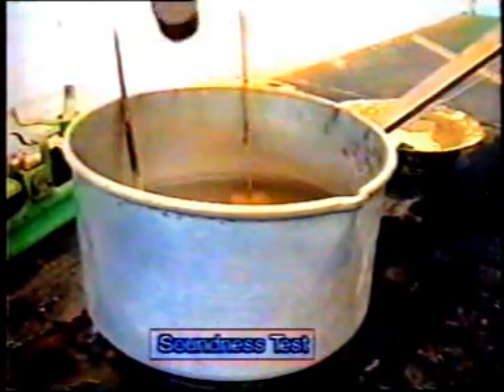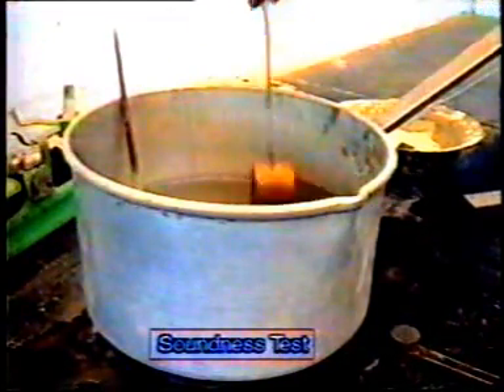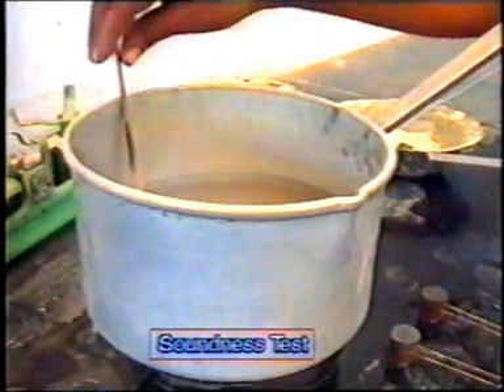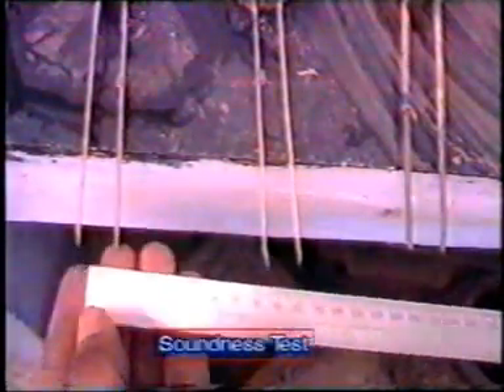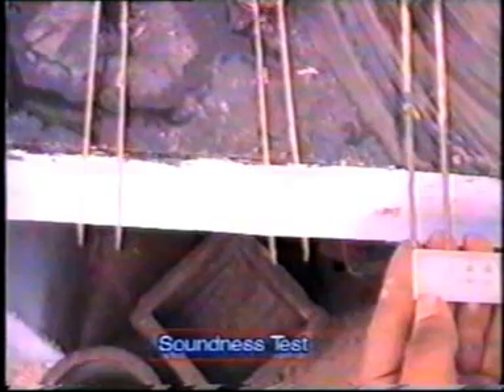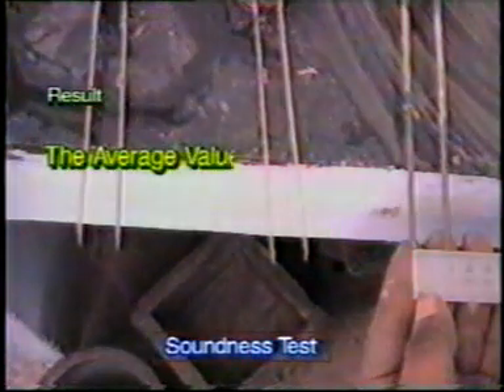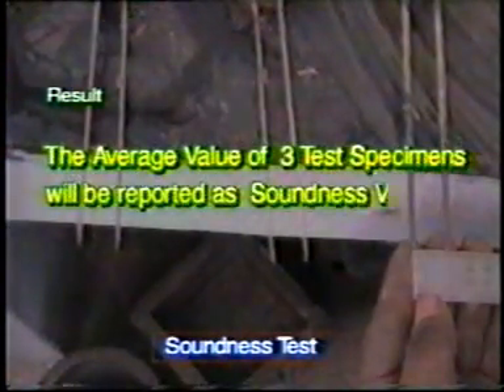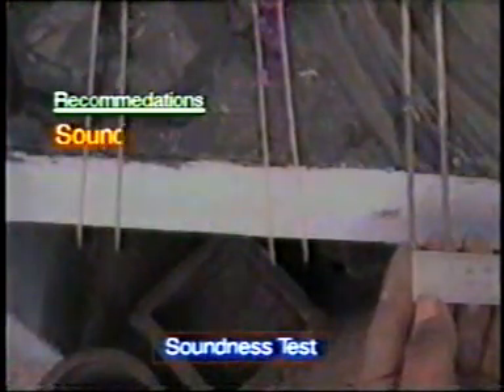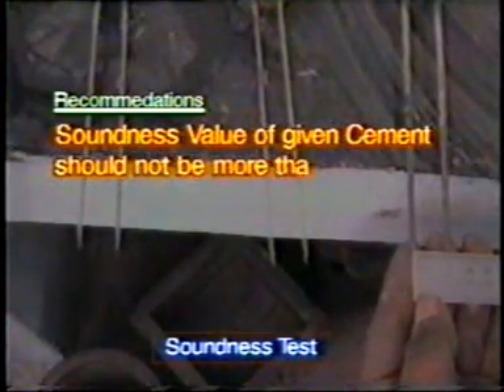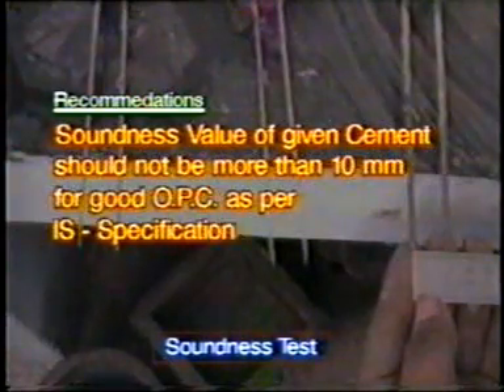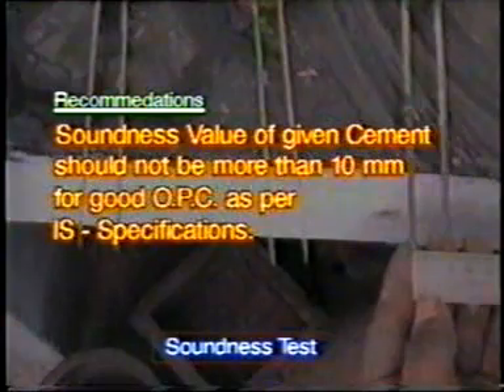Take out the sample now and allow it to cool to room temperature and measure the distance between the two indicators of the split cylinder at the point ends. Let this distance be L2. The difference between the values L1 and L2 is called the soundness of cement. An average of 3 such samples will be reported as the soundness value of the cement. Recommendations. Soundness value of a given cement should not be more than 10 mm for a good ordinary Portland cement as per IS specifications.